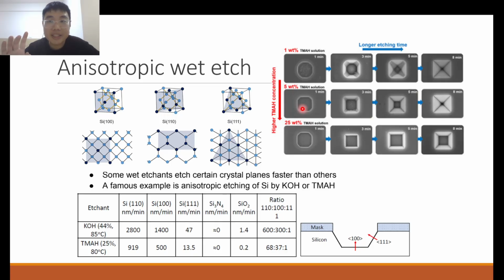Yes, actually there is a case: the anisotropic wet etch of silicon. So why is this so? This is because certain crystal faces of single crystalline silicon are easier to etch by these etching reagents, KOH or TMAH. TMAH is tetramethylammonium hydroxide. These etching agents etch certain faces of silicon at a faster rate than others.